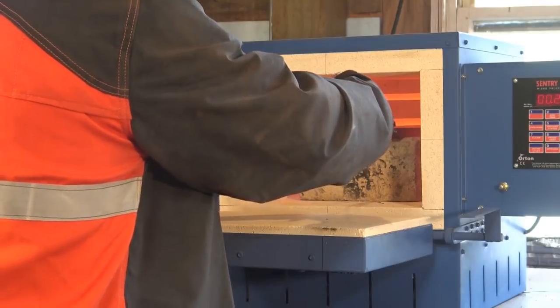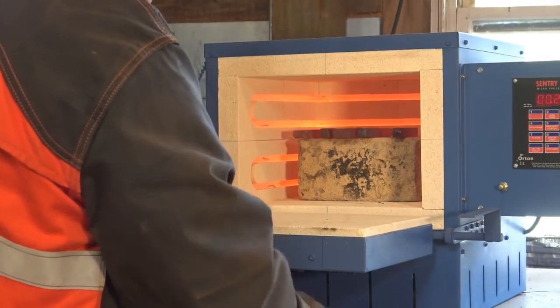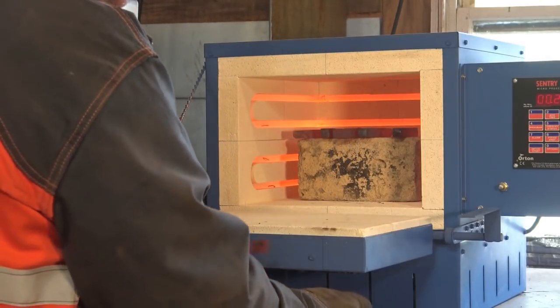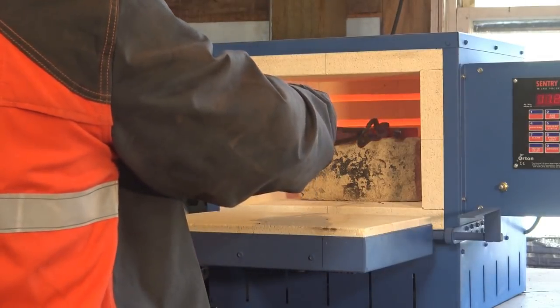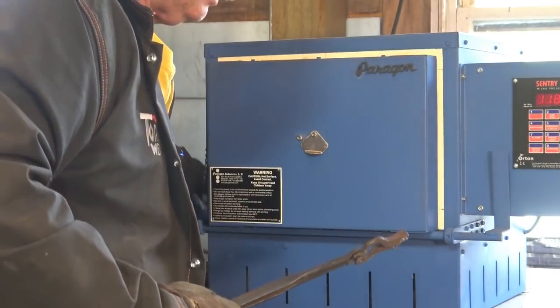5160, which has a critical temperature of 1525, is not magnetic. So the 5160 is 125 degrees too cold to harden, but it has lost its magnetism. So that's starting to get a little bit more difficult to judge by eye if you're doing this in the forge.